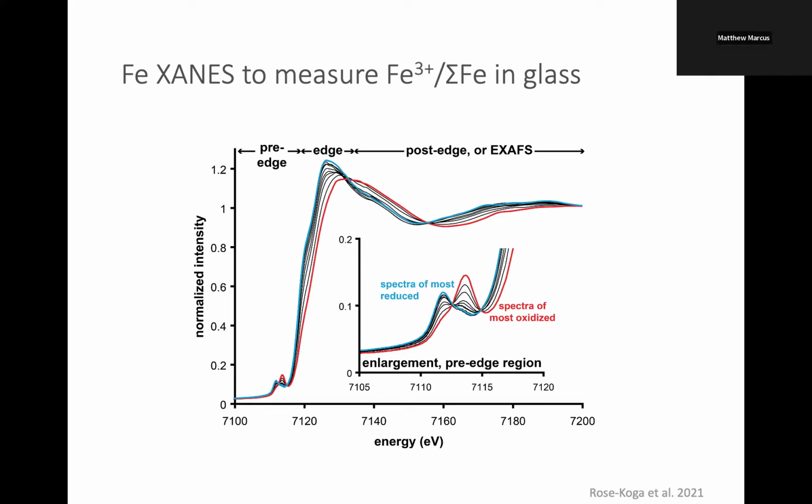Oh, there's the button. Yeah, it's kind of talking about the radiation damage. It's another unusual feature of it, aside from the fact that cooling makes it worse, is that it's oxidation rather than reduction. And I was wondering if the sample was in air or inert gas. The samples were analyzed in air. It does seem to be kind of an interesting form of beam damage compared to other observations that people make.